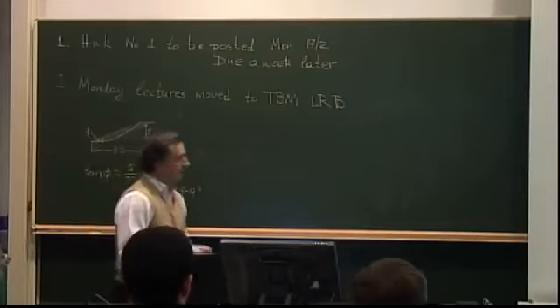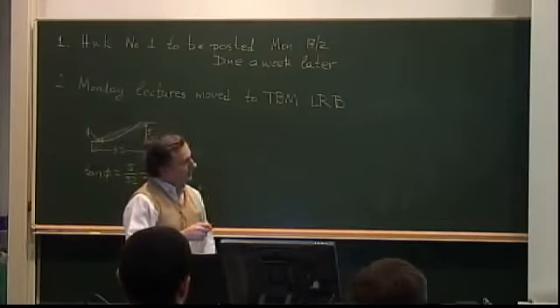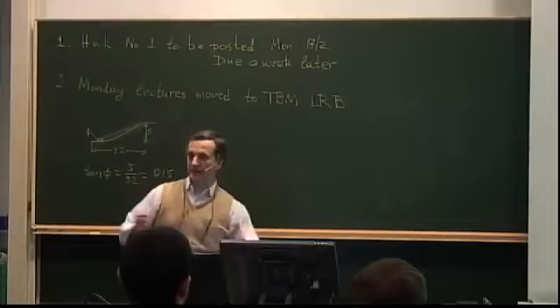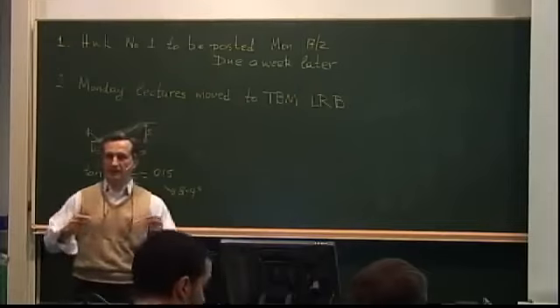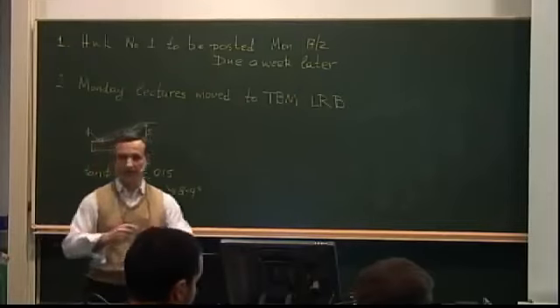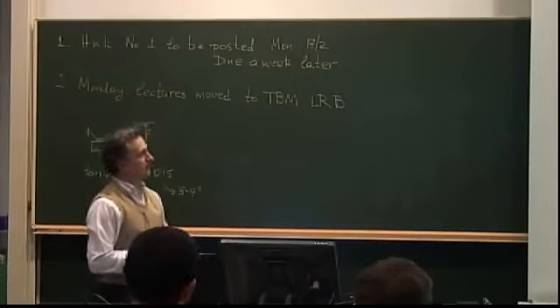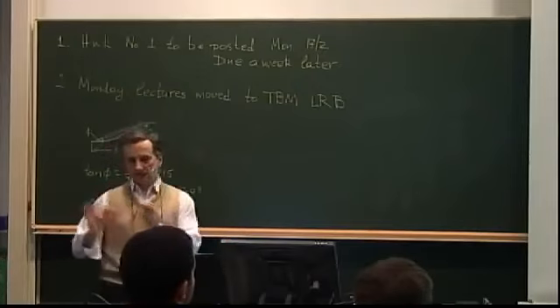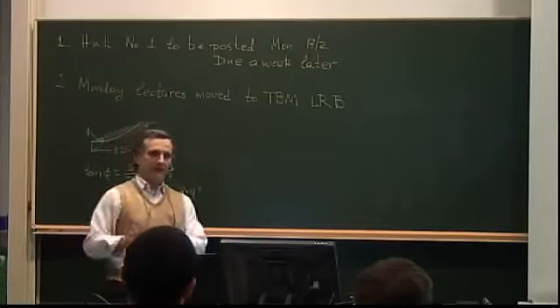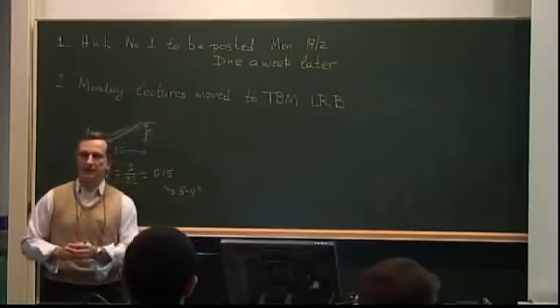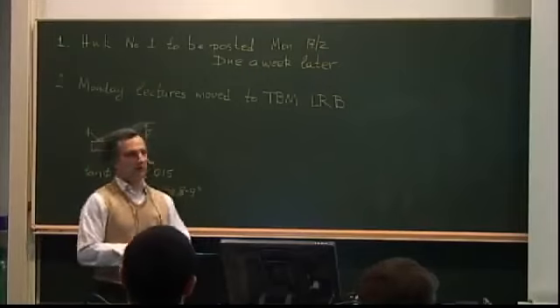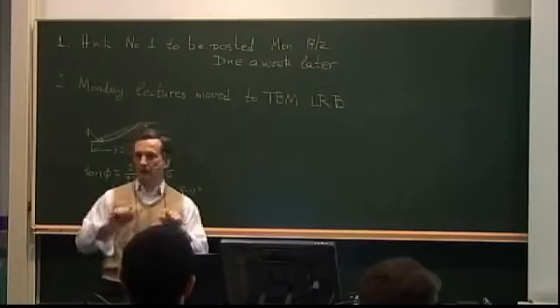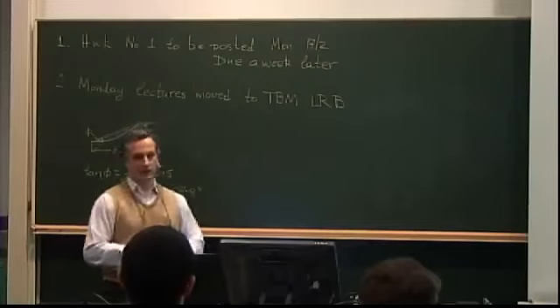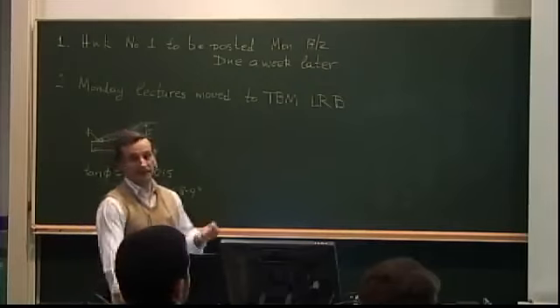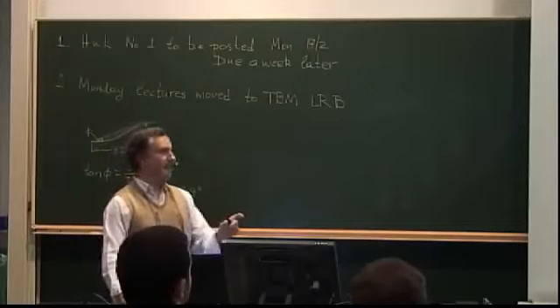And in general, because there are 5 different modes, somehow they will interact, so you need a criterion or a method to put them together, and that's what's called a failure criterion. That's what we will end up doing, but let's say we recognize at this point that this is not very accurate because, as I mentioned, what happens at the local matrix and fiber level or scale can be quite complex and might be different than what we think at the ply level.